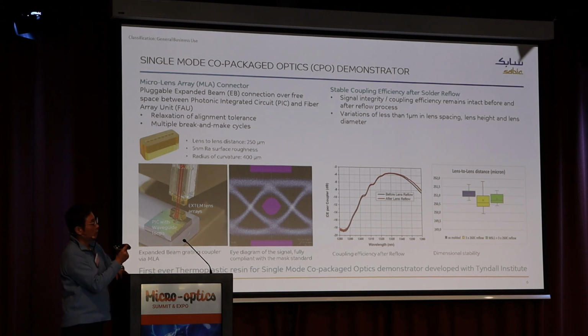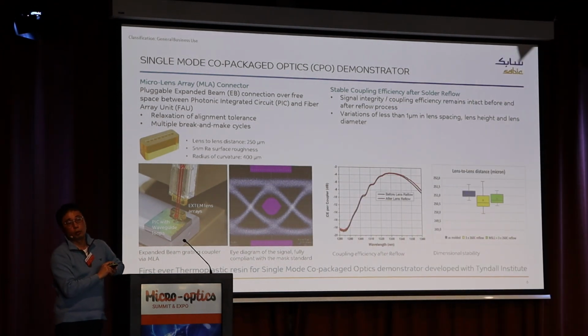But this MSL condition is not only material dependent, it can also depend on the part design. For example, if you have a thicker part, then the moisture can take more time to escape during the earlier temperature pick up in the reflow cycle. So in that case, it may pass MSL3 conditions, for example.